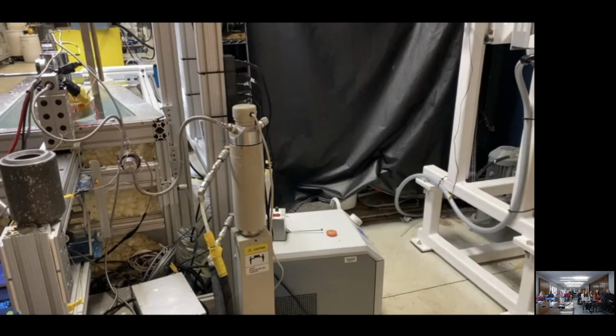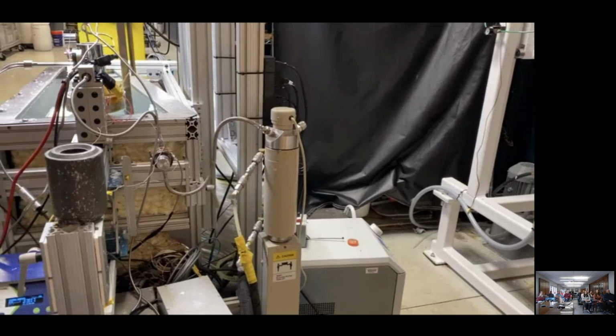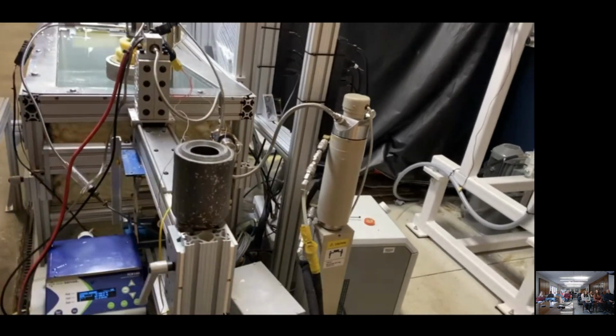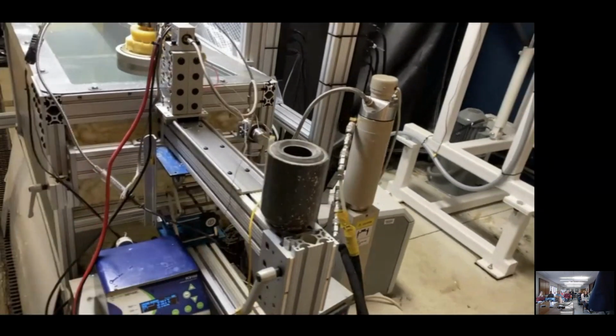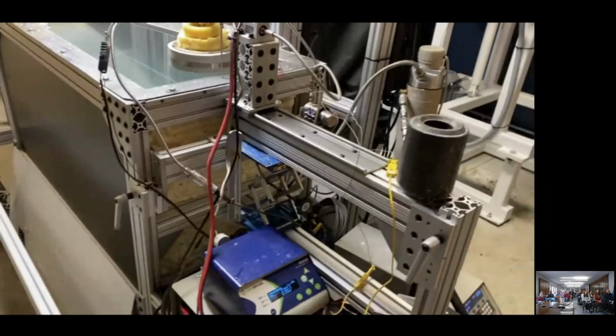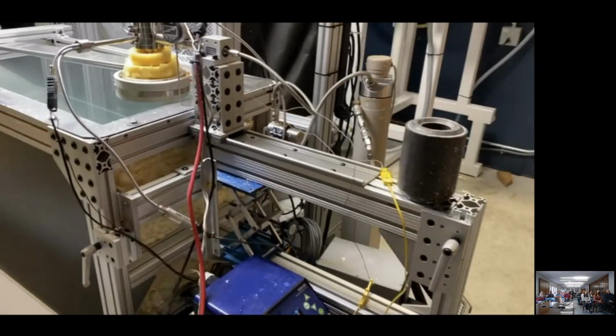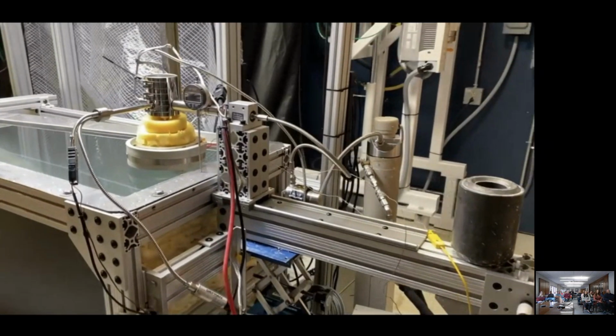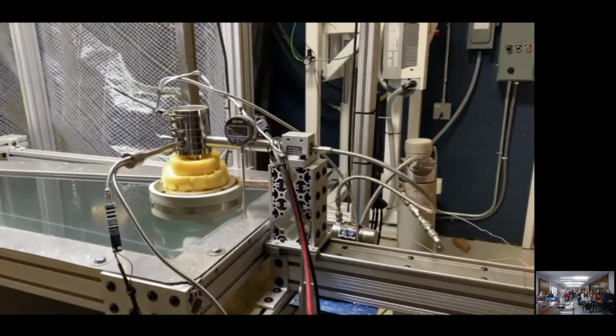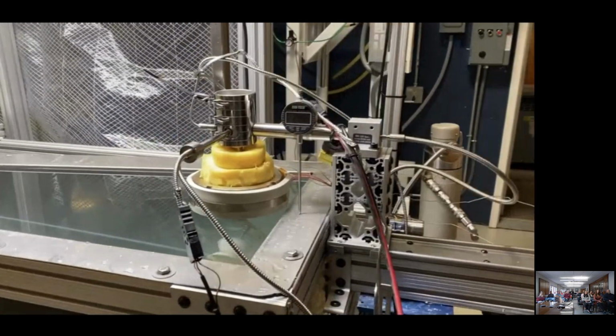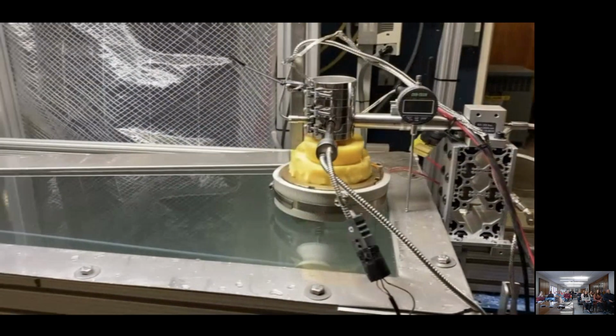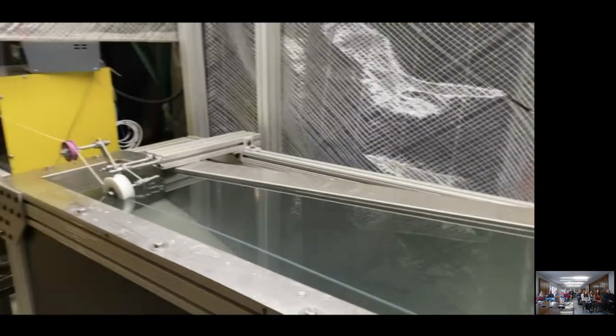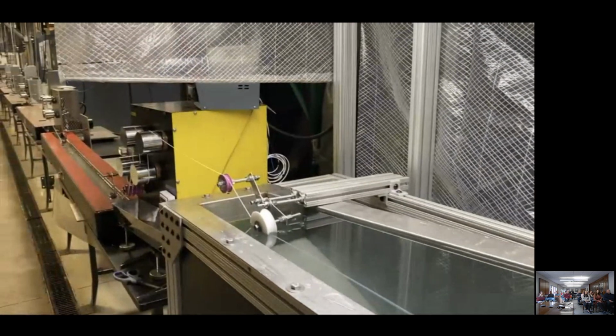In this case, we'll have experimental polyacrylonitrile dope, our solution, in this pump. We'll pump it through a filter and then over to the spin head with this yellow insulating foam on it. The filaments form in the air gap and then are drawn down into this bath, forming. In this case, it's a 100 filament tow being formed and taken up. When I say tow, that's just the unidirectional collimated bundle of the filaments. In industry, that would be more like 3,000, 12,000, or 24,000.